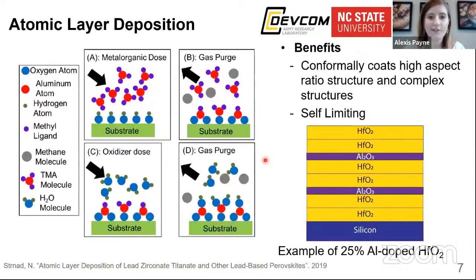So now that I've introduced what our thin film material is, I'll now tell you how we grow it. So we grow our thin films via atomic layer deposition, which is also known as ALD. And ALD is a chemical gas phase thin film deposition method based on sequential self-saturating surface reactions. So 2 or more precursors, each containing different elements of the material being deposited. In our case, our precursors contain aluminum, and then another one contains hafnium.